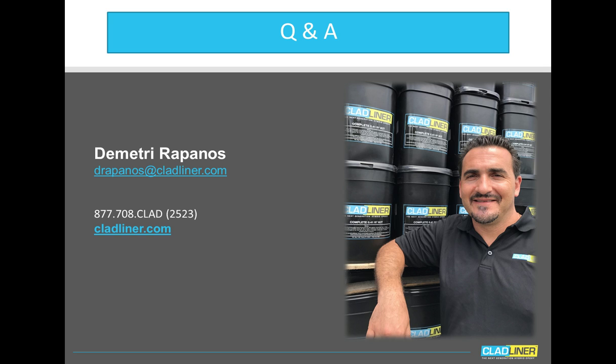That's a great question. When doing manhole rehabilitation, any contractor or municipal folks that have actually been down in the structures know that in most cases, it's almost impossible to get those structures completely dry, regardless of humidity or lack of humidity. The Cladliner was specifically designed to be applied in humid but also moist and or wet environments that we find in those kind of structures. In fact, the wet surface is what we want to apply to. So typically what we recommend with contractors is as soon as the power washing phase is completed, that's when the Cladliner would be applied while the substrate is still moist.